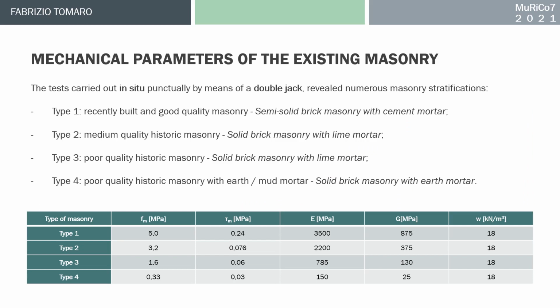The tests carried out in situ punctually by means of a double jack revealed numerous masonry stratifications. For example, type 1 is recently built, good quality masonry; type 2 is medium quality historic masonry; type 3 is poor quality historic masonry; and at the end, type 4 is poor quality historic masonry with earth and mud mortar. The table shows the mechanical properties derived from the investigation for each masonry type.